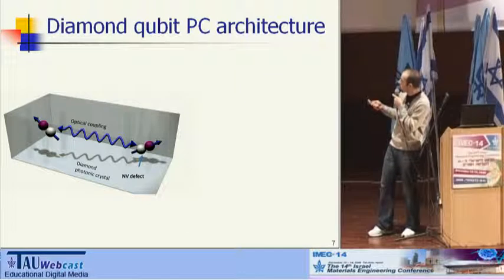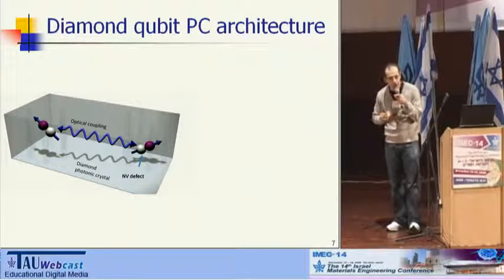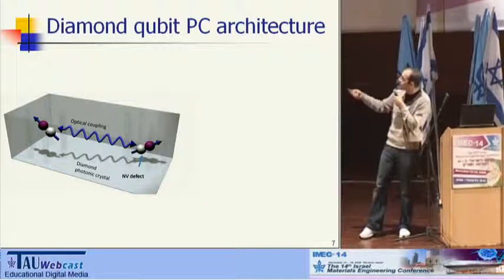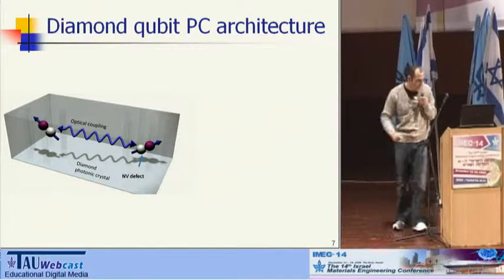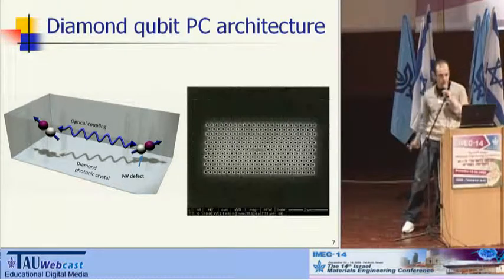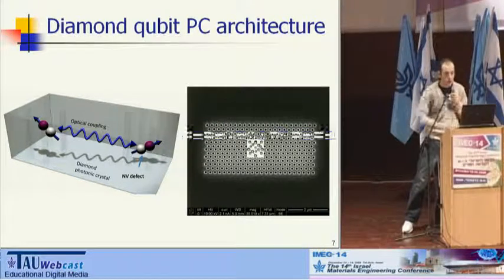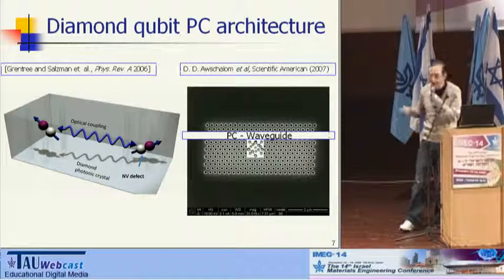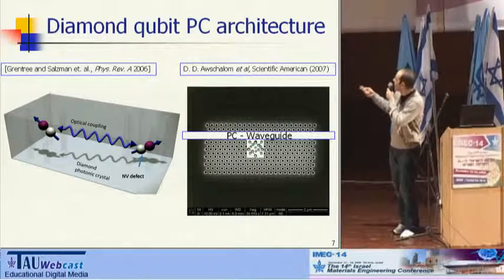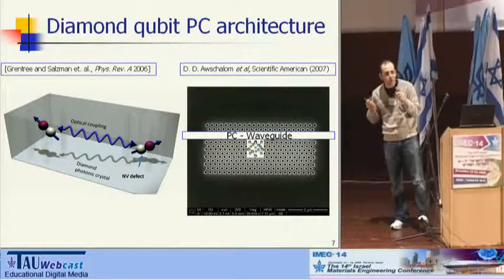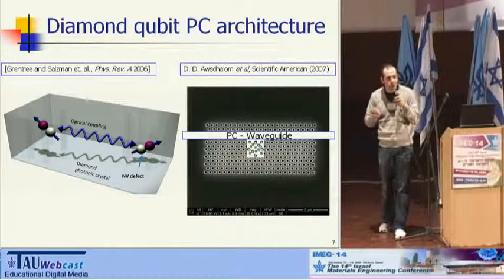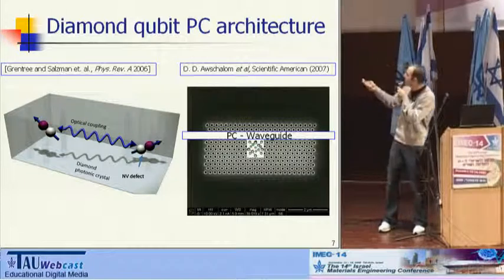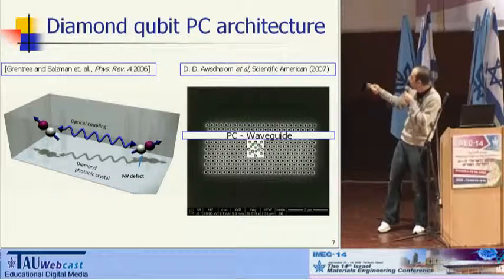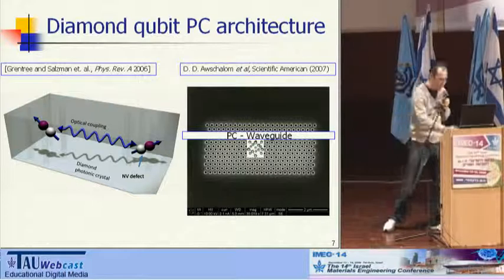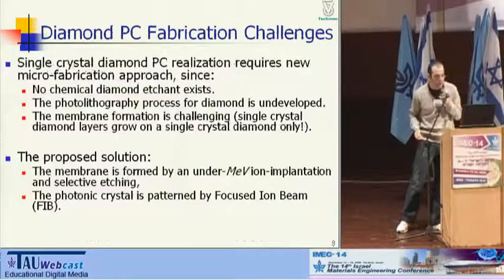Each NV center is localized to the cavity, and the interaction between distant NV centers, which might be positioned tens of microns away, is via emitted photons. So in this case, we've got to have the photonic crystal cavity. We've got to fabricate the photonic crystal waveguide and position the NV center inside. Throughout all this work, we use type 1b diamond, which is enriched with NV centers, so we do not have a single NV center, but the whole area here is enriched with nitrogen. Now, let's go for the fabrication.